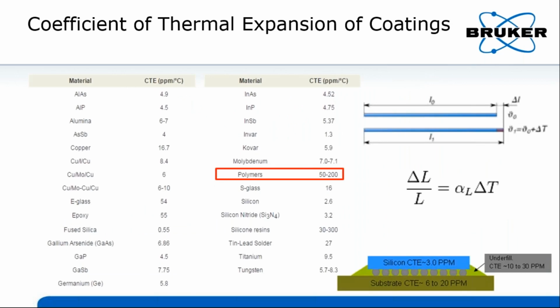The final topic of high temperature measurements is the coefficient of thermal expansion, CTE. Here we have the definition of linear CTE, which is the ratio of the size change to the original size divided by the temperature change, delta T. On the left-hand side is the list of CTE values for materials typically used in semiconductors, including silicon with a CTE of 2.6 ppm per degree, and copper with a CTE of 16.7 ppm per degree. Today we have a case of polymer used as underfill, which has a reported range of CTE from 50 to 200 ppm per degree.